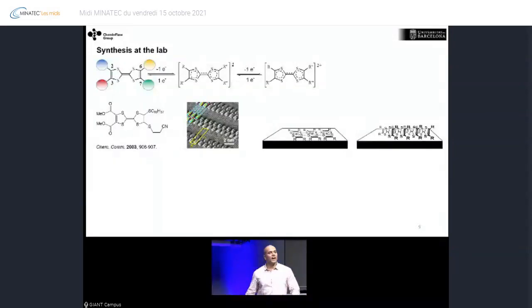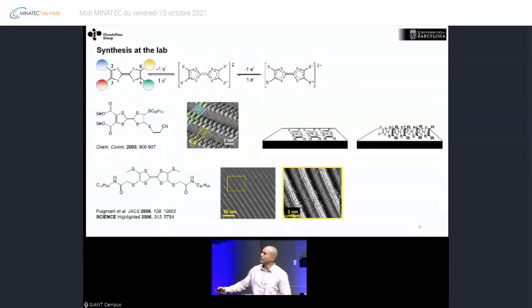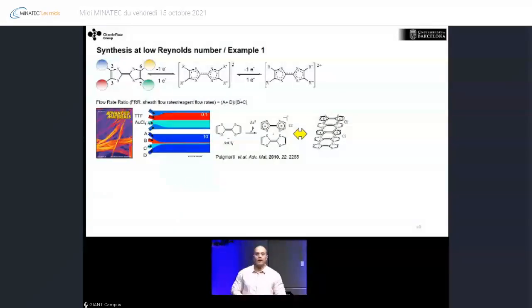This is what I told you. As an organic chemist, we go to the lab, we put different functional groups, now amides, and now because of the hydrogen bonding, what we can achieve is this perfect organization of the molecule on the surface, which is now organized perpendicular to the surface. Okay? And this can be clearly seen here. So here molecules are lying flat, and here they are tilted with respect to the surface. Okay, so now that we have this in mind, let's see what happens when we use microfluidic technologies.